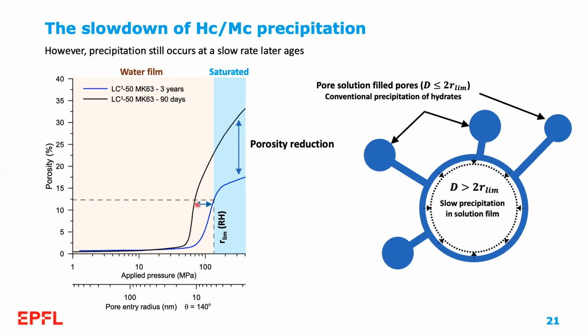In this case, we propose that there is a dual mechanism. In small pores that remain saturated, we have conventional precipitation of hydrates because we have pore solution saturating the pores. And in pores that are larger than that, so they are only partially saturated or covered by a film lining the internal surface of the pore, we have slow precipitation in this solution film that covers the surface of the pore.